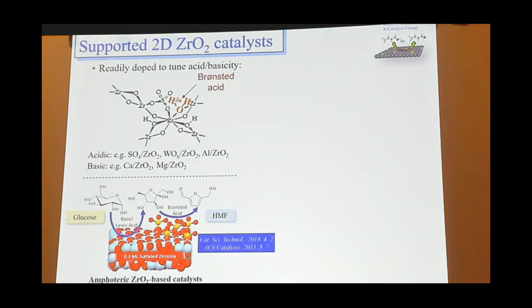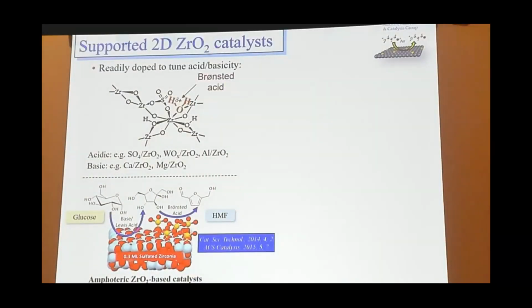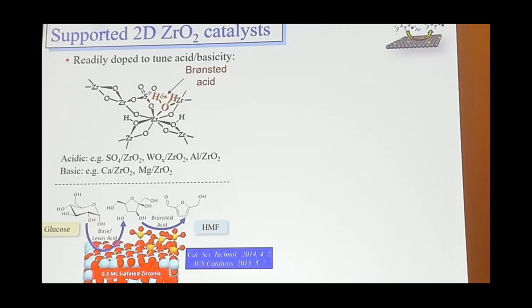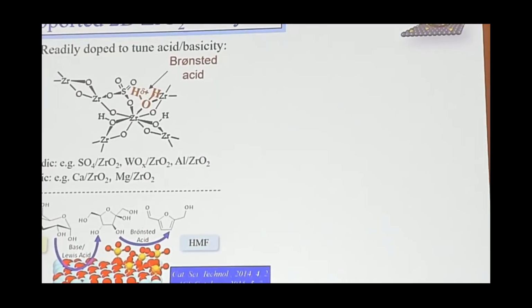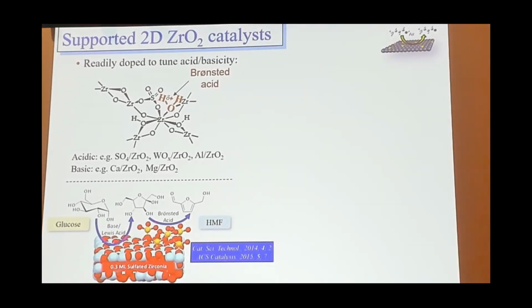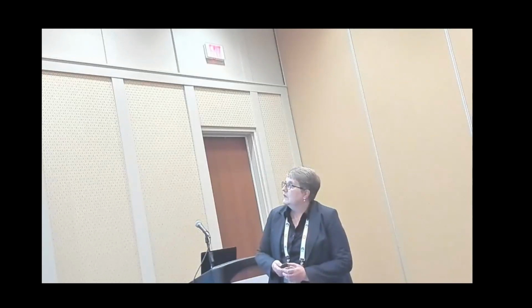So one of the things we've been looking at in terms of cascade reactions is the production of HMF. If you take glucose and transform that to HMF, it's not a one-step process. The first thing you have to do is isomerize glucose to fructose, and then you can do an acid catalyzed dehydration to produce HMF. So what you actually need in order to do this is either a Lewis acid or a Lewis base to do the isomerization, and then Brønsted acidity to do the dehydration. So with zirconia, by partially sulfating the surface, you can get a balance of Lewis acidity and Brønsted acidity in order to effect that transformation.